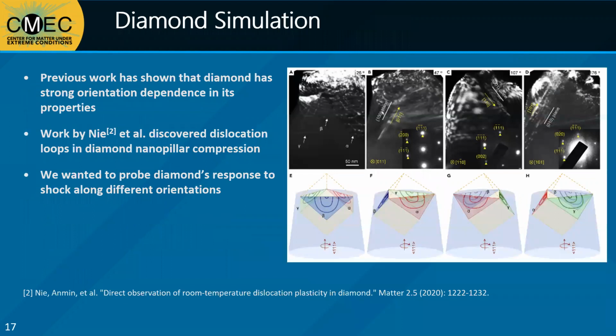Diamond's famous hardness and its bond strength mean that it is difficult to observe the presence of defects in diamond. However, previous work by Nie et al. created diamond nanopillars with a focused ion beam and then performed in situ compression in transmission electron microscopy. They observed the presence of dislocation loops when the samples were compressed along the 011 and 111 orientations. These loops propagated along the 001 planes in their experiments, forming a trio of loops around the 111 axis. These static compression experiments showed that the anisotropic nature of defects in diamond have a very important relationship with the loading direction.